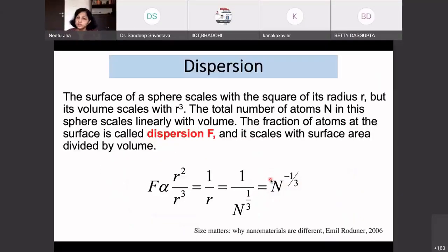And this property is called dispersion. Dispersion is a parameter which you can measure for the particles, and it is the fraction of atoms at the surface. It scales with surface area divided by volume. So for mostly spherical particles, you can say that dispersion is inversely proportional to the radius of the particle and the cube root of the total number of atoms which is making the crystal, or which is making the stable nanoparticle.